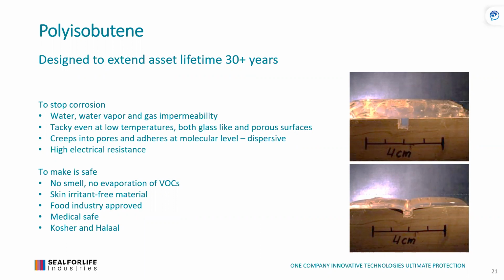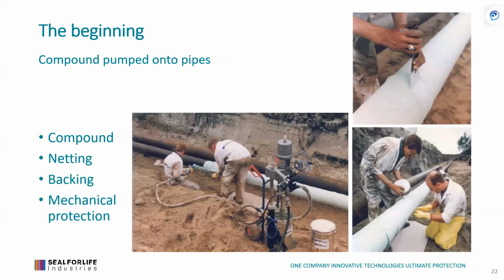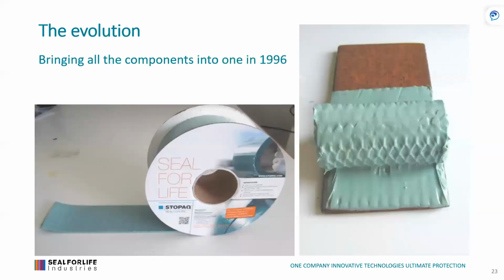BASF invented the product in the 1930s for other reasons in those times, but at the same time, it was proven that the product, because it has been filtered so many times, removal of free radicals, it actually came to a point where you didn't have to do much to it, and you had lifetime out of it. So in the beginning, make the product, make the compound, pump it onto the pipe, then put a netting to hold it all together, and put mechanical protection. Labor intensive, you don't have even thickness.